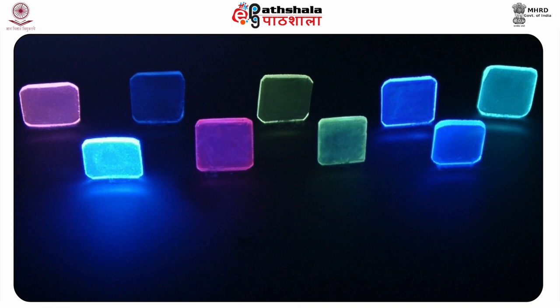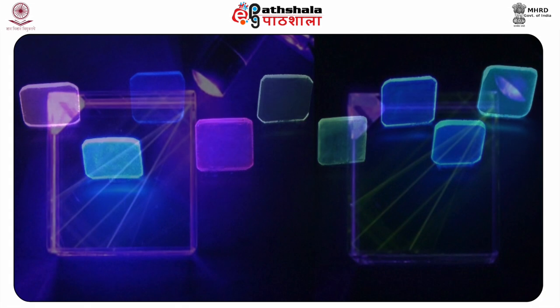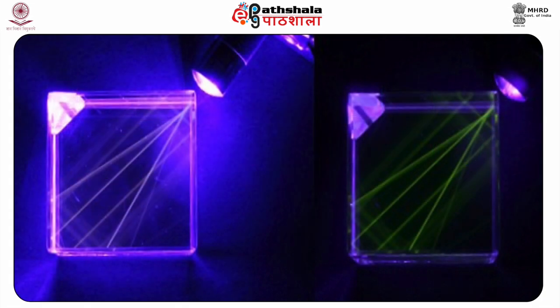similar size and thickness, and they are to be thoroughly washed with acetone or any other suitable solvent to remove any grease or dirt. When there is a clear difference in the fluorescence of the two glasses, it indicates different source of their origin. On the other hand, the similarity in fluorescence by itself cannot be conclusive proof of source correspondence, and further tests are to be conducted to arrive at the possible commonness of the origin.